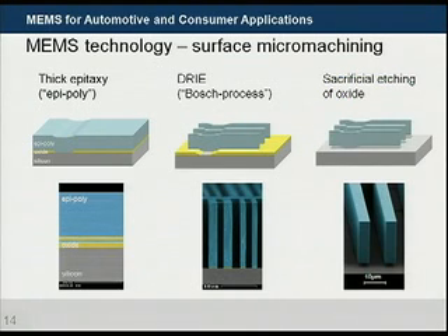The last step is then the removal of the sacrificial oxide, this yellow layer, and you see some of the polysilicon has been deposited directly onto the substrate, so it's fixed, it's anchored to the substrate. The other parts are freely movable, so we can make fingers, bridges, masses, etc. onto the wafer.